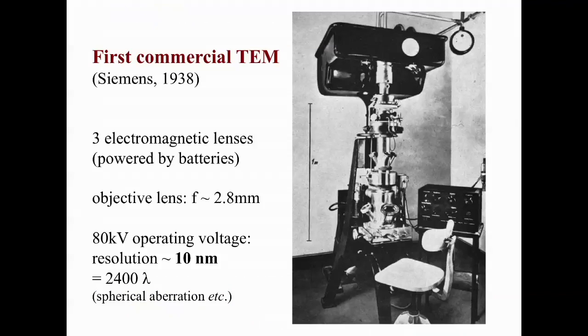This all sounds highly promising, but when the first commercial transmission electron microscope appeared in 1938, its resolution was 10 nanometers. This is about 50 atoms wide and over 2,000 times the electron wavelength. The reason, of course, was imperfect lenses. The magnetic fields used to focus the 80 kV electrons suffered from spherical aberration.